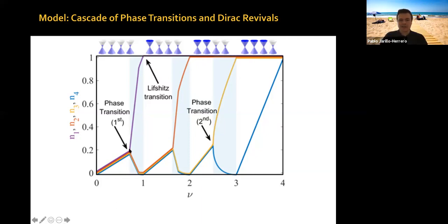So the system decides to start filling one flavor completely and empties all three other flavors. And then the chemical potential, after it reaches here and fills one of the flavors completely, gets completely reset to charge neutrality. This is this Dirac revival. So the system looks again as if it is at the charge neutrality point. And then it continues. You start filling the remaining, in the simplest model, the remaining three flavors. It could be actually somewhat more complicated. We have some indications now that it may be more complicated, but in the simplest interpretation, you start filling the other remaining three flavors uniformly.